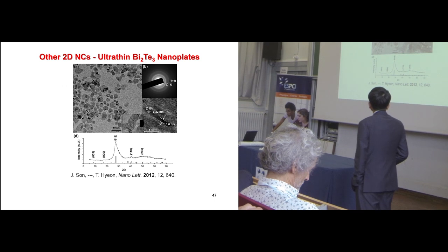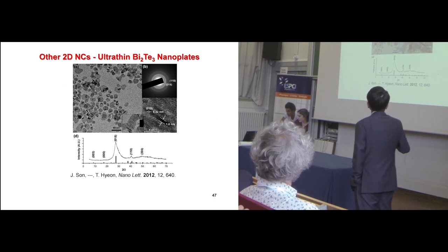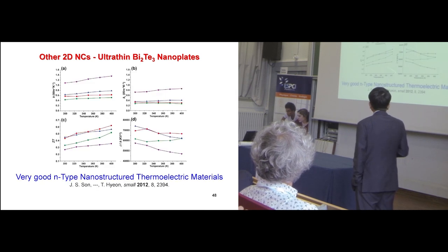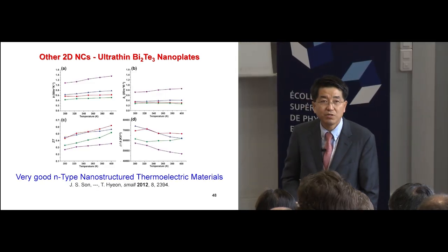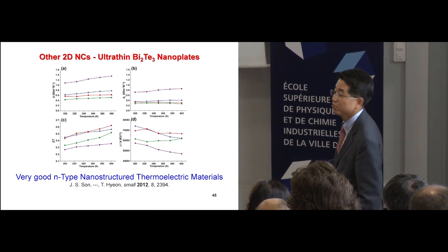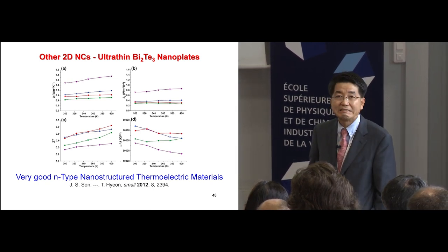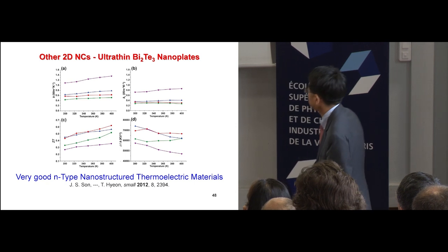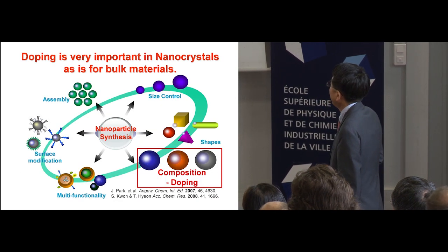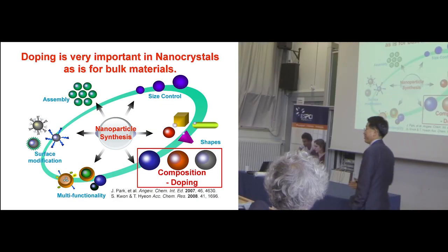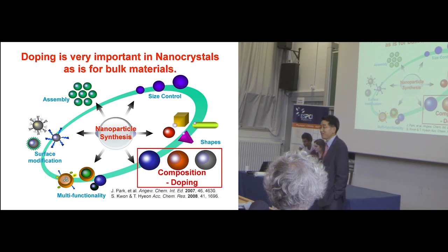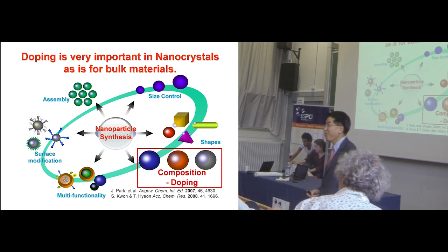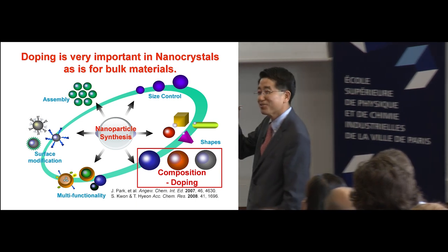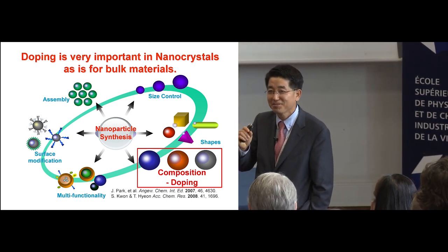More recently, this is bismuth telluride. We made the nanoplate and looked at its thermoelectric property. It turned out to be not that great, but we got a ZT value of about 0.6 using this kind of material. I'm sorry, David, tomorrow David's main topic is going to be doping, but let's say this is a small bite of the doping.